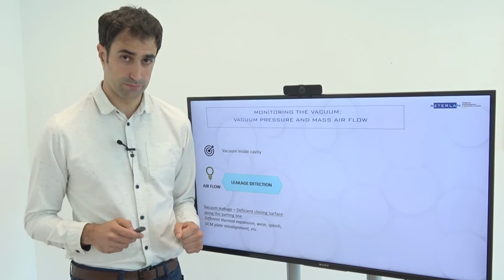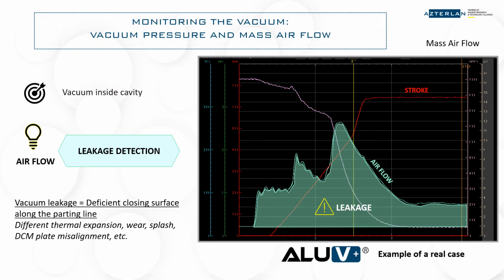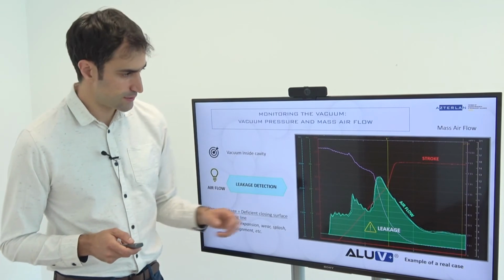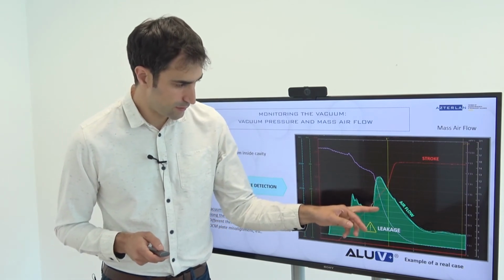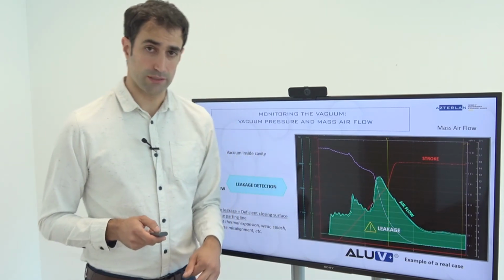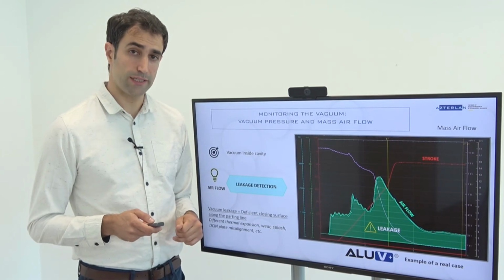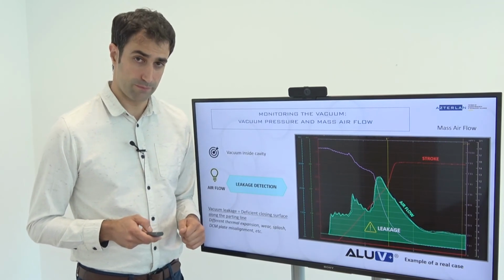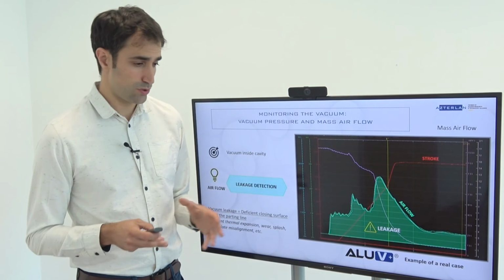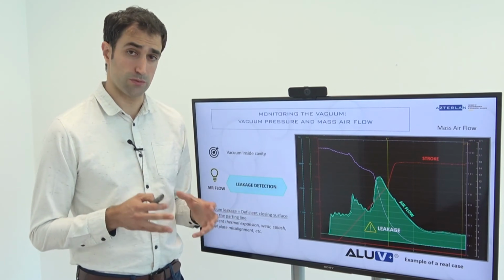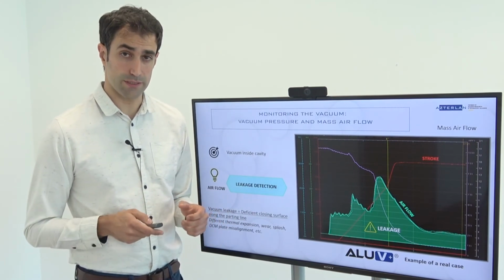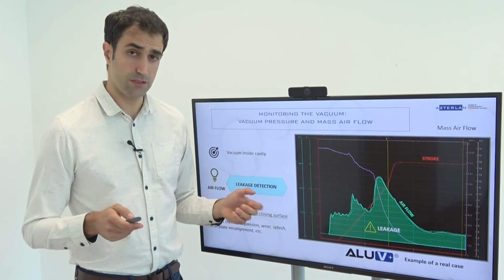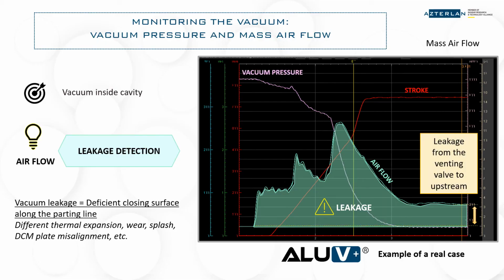leakage detection. For example, we were able to detect a leakage problem through the airflow monitoring. We recorded a suspiciously high amount of airflow. Besides, after the die filling, the airflow remained constant, meaning that there was a leakage issue in the venting valve. The reason was the different thermal expansion between the venting valve and the die cavity steel that caused the deficient closing surface and obviously the leak.